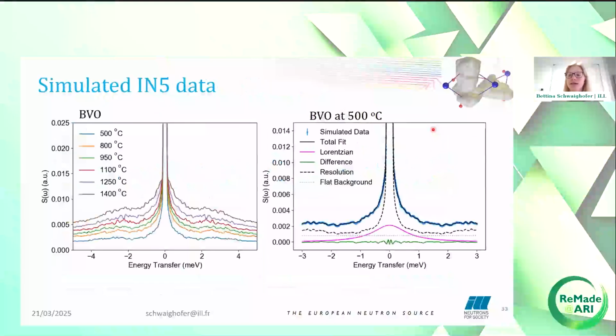With this we wanted to see if we can directly compare our simulated data to the experimental data obtained on IN5. We therefore used the resolution we had on IN5 to simulate the S of omega, and fitted it exactly like we did with the experimental data, using a convolution of resolution and delta function for the elastic peak and a Lorentzian for the QENS broadening.